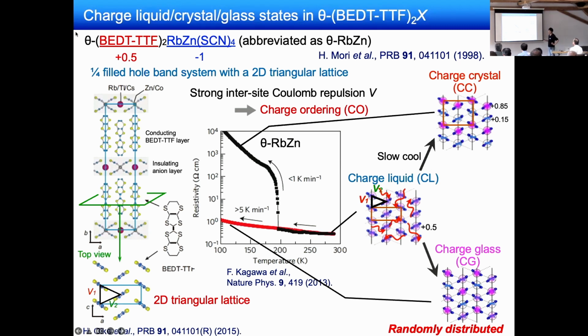Okay, so our target materials are the theta-type BEDT-TTF compounds, which have a layered structure consisting of conducting BEDT-TTF layers and insulating anion layers. The charge transfer between these two layers leads to a quarter-filled band system with a two-dimensional triangular lattice. For example, this theta rubidium zinc compound shows a charge order transition due to the strong intersite interaction at about 200 Kelvin. At this charge order transition, the system transforms from charge liquid to charge crystal states. But very interestingly, this charge crystallization can be avoided by rapid cooling faster than a critical cooling rate. And then the system enters a glassy state where the charge carriers are randomly distributed.